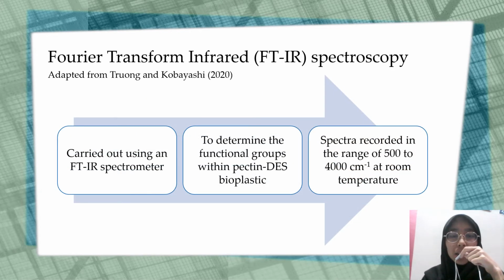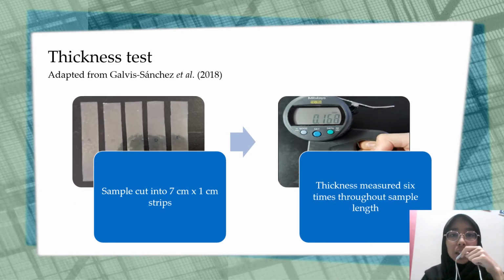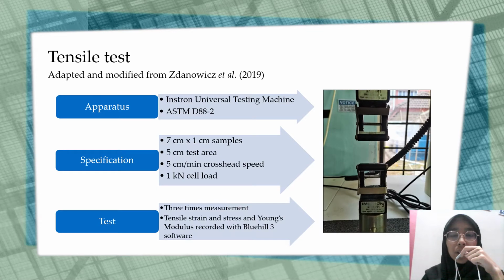FTIR was done and the spectra was recorded in the range of 500 to 4000 reciprocal centimeter at room temperature. The thickness of the bioplastic strips were measured 6 times throughout its length and the average thickness was calculated. Tensile test was done according to ASTM D882 with the following specifications, and the test was repeated 3 times for each bioplastic sample.